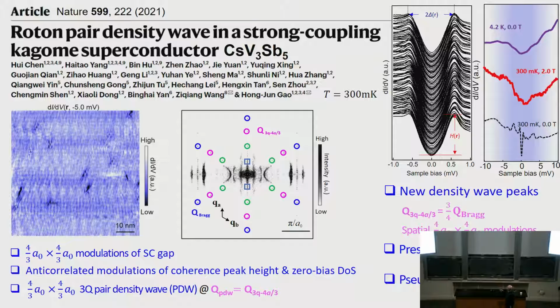Pseudogap, let me show you the pseudogap behavior. This is over a wider range of energy. And this is 300 millikelvin, 0 Tesla. The superconducting gap is here. These other peaks are mysterious. We don't know what they are. We think these are actually peaks induced by the pair density wave order. But here you can apply a 2 Tesla field that wipes out superconductivity. You see the pseudogap that's left behind. This is at very low energy. This is not the CDW gap. That's 50 millivolts. This is really at about 5 millivolts. Or you can switch out the field and go above Tc. You still see this gap. So the pseudogap is there, just like in the cuprates.